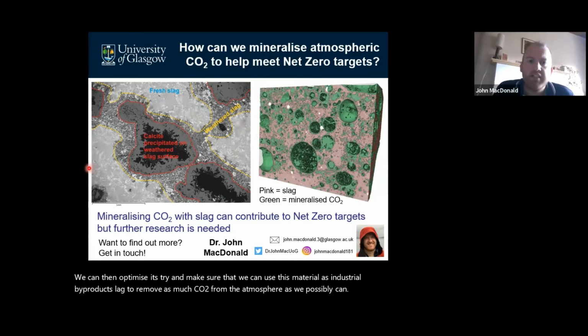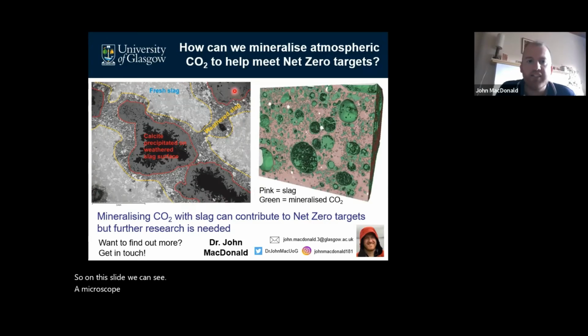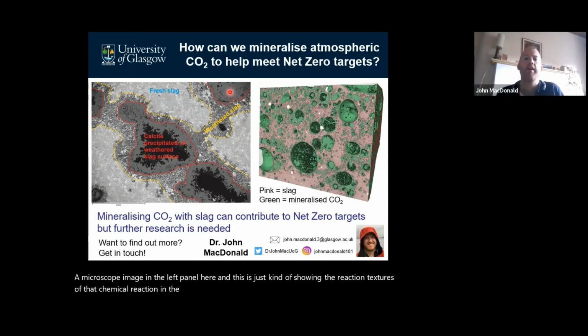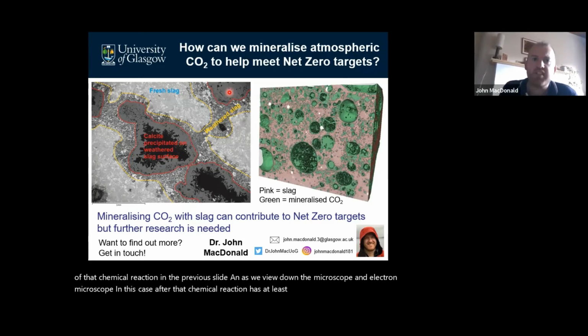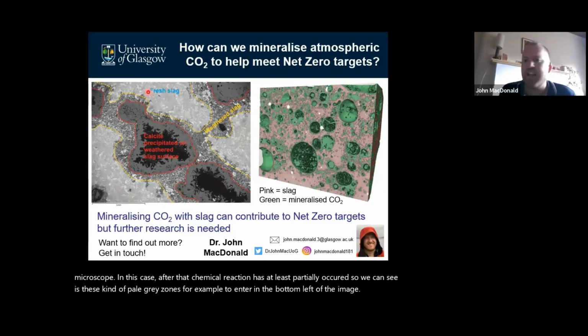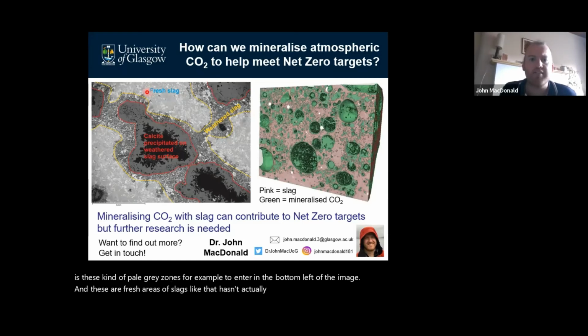So on this slide, we can see a microscope image in the left panel here. And this is showing the reaction textures of that chemical reaction on the previous slide, as we view down the microscope, an electron microscope in this case, after that chemical reaction has at least partially occurred. So what we can see is these pale grey zones, for example, down here in the bottom left of the image. And these are fresh areas of slag, so slag that hasn't actually reacted with the CO2 yet.